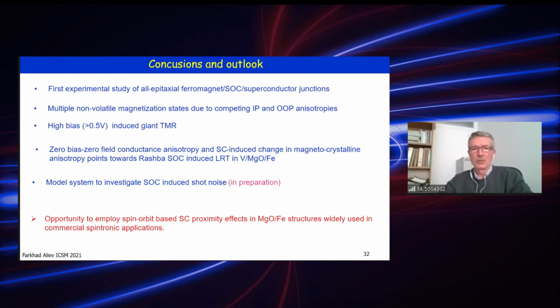So I conclude that we present the first experimental study of epitaxial ferromagnet-superconductor spin-orbit coupled junctions. Different non-volatile magnetic states could be created in such systems for in-plane and out-of-plane anisotropies.